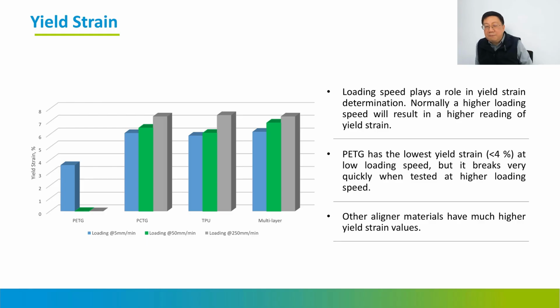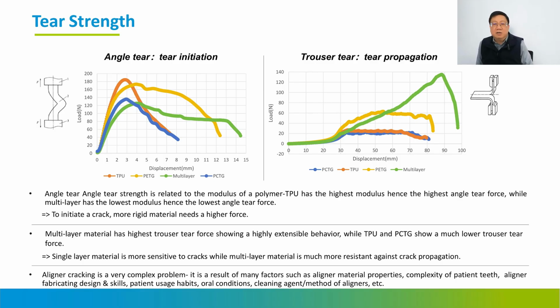In the past, a lot of people used copolyester as the aligner and also as a retainer. Because it has a very low tear strain, it is easy to crack. For this reason, single layer copolyester is used much less right now. This kind of scientific measurement method measures the crack resistance. The area they cover means the polyurethane uses more energy with larger tear strain. You can see the tear propagation and the energy under the curve is bigger. So multi-layer can absorb much more energy than single layer, which means its crack resistance is much better.